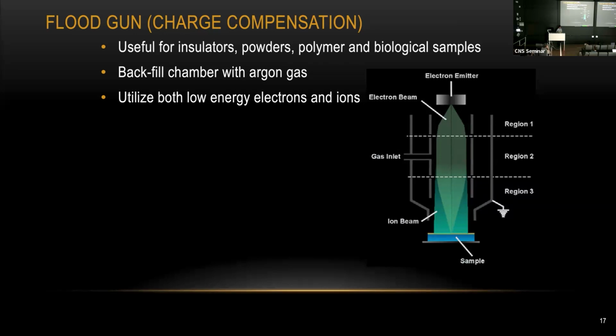What the flood gun is doing is, the first thing, you try to backfill your chamber with some argon gas, so that allows argon molecules inside the chamber. And we also give you some low energy electrons and ions to neutralize the entire surface.